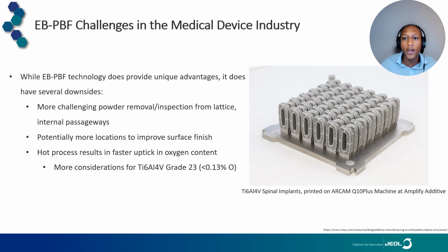But not only process control in blasting the powder, also how you inspect. How can you prove that each one of these implants has had powder completely removed from the lattice structure and the internal passageways? Methods to ensure your process control and removal of all that powder is a bit more challenging for electron beam powder bed fusion because of the sintering. Whereas with laser powder bed fusion, because there is no sintering, the powder particles can be more easily removed, and it is easier to prove that the powder has been removed and cleaned off from lattice structures.